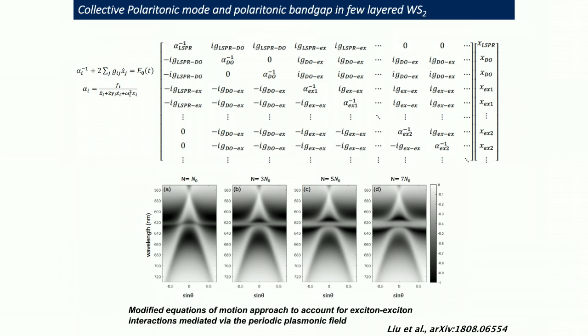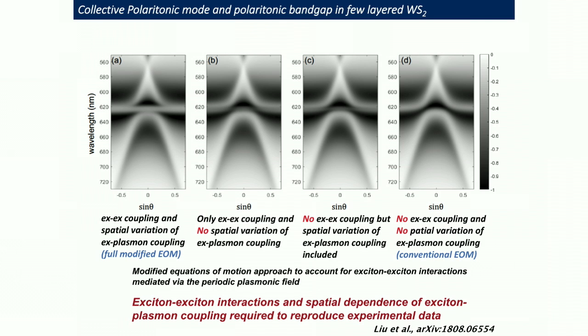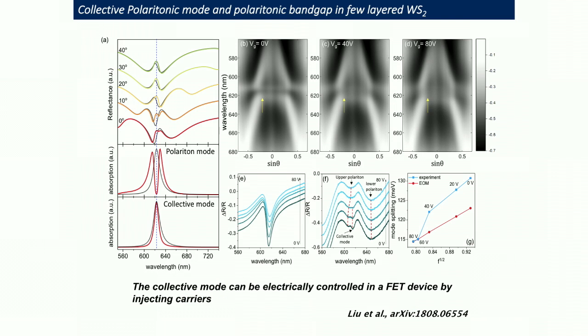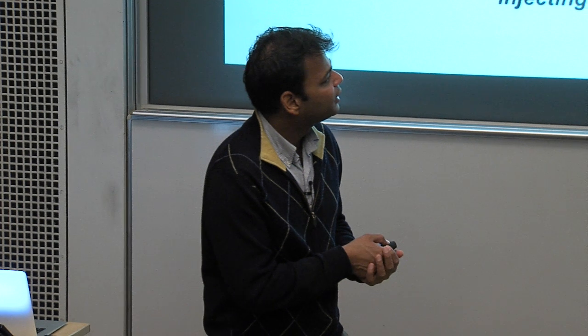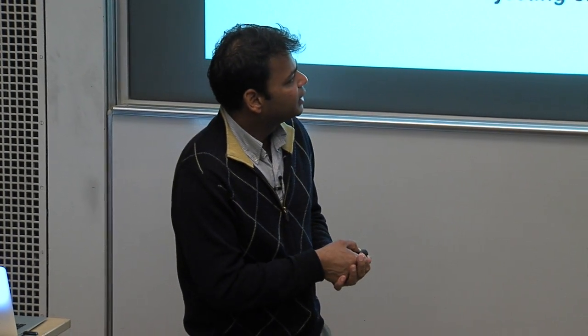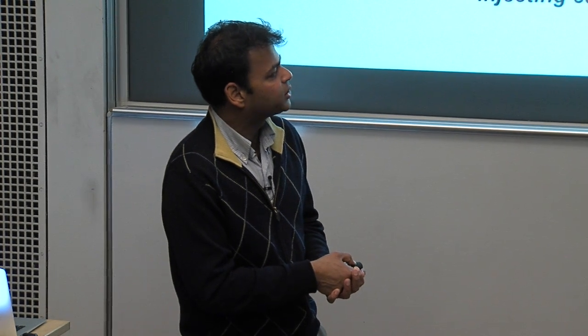When we diagonalized the whole thing, these are simulations using this matrix with increasing number of excitons. As you can see, when we increase the excitons over a certain limit, we start getting this flat mode and the polaritonic band gap. So all these features can be extracted. This is telling us that exciton-exciton interaction mediated by this periodic plasmonic field is really important to produce all these new features that we are seeing. Since we can integrate this into a transistor, we could extract something very interesting. In a regular polaritonic system where the excitons are not interacting with each other, the splitting, the anti-crossing behavior, scales linearly with the square root of the number of excitons in the system.